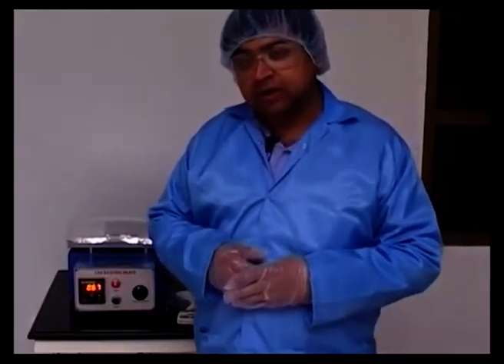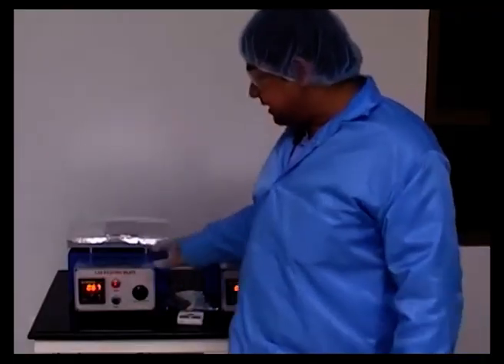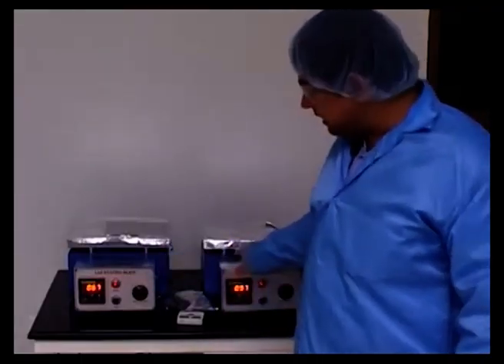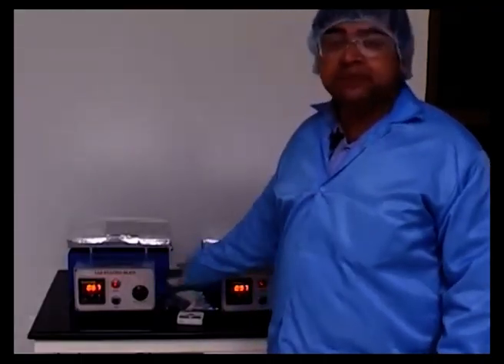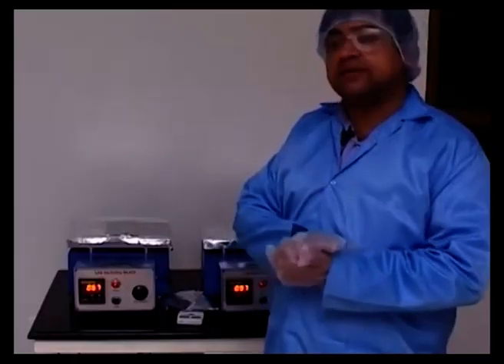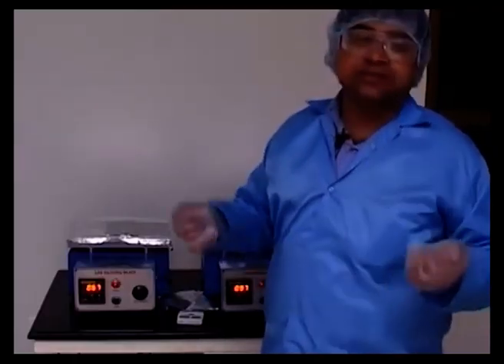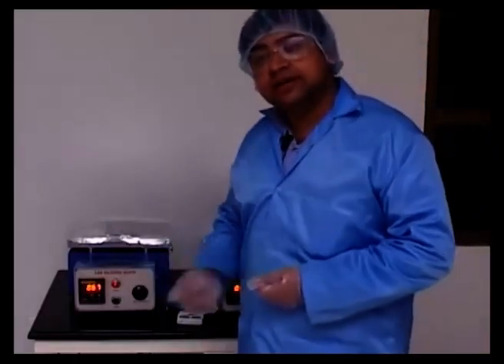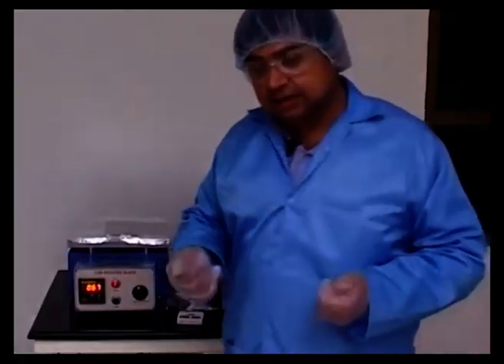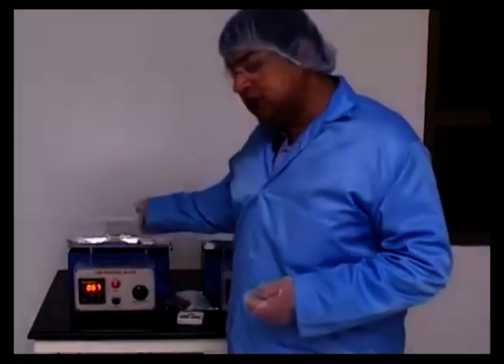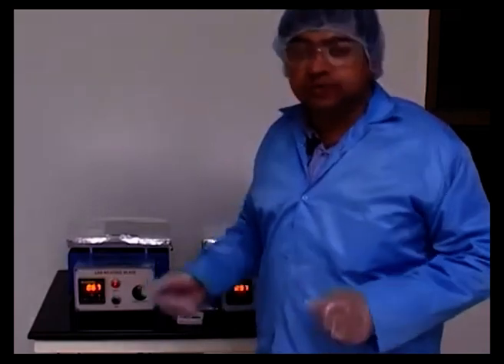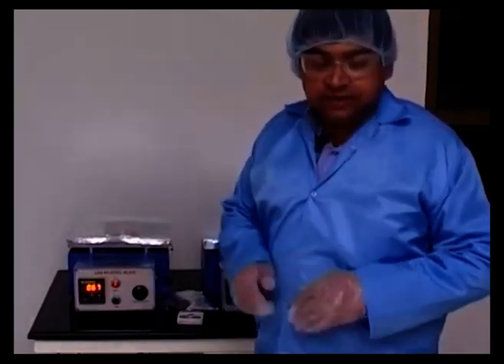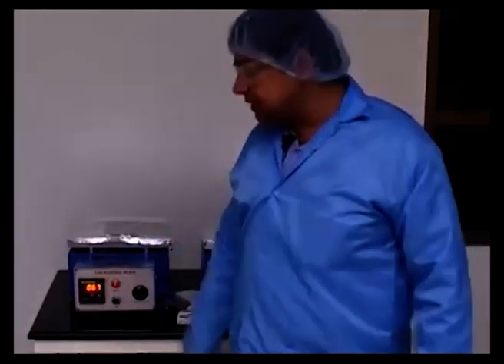So therefore, we use hot plates for this purpose. Here, as you see in this particular illustration, I have two hot plates. They have been preset to temperatures of 65 and 95 degrees Celsius, and each of these steps would have a certain time associated with it. So the spin coated resist on the wafer would be brought in, and these plates would be used for heating so that we can get a cured film of the resist on the surface.